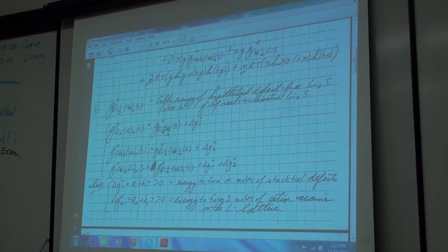Is there any relationship between the site fraction of the vacancy in the cationic sublattice and the site fraction of the lithium in the interstitial sublattice? Well, no, it depends on which side of the stoichiometry you are. They're both dependent on the overall composition. But yes, there definitely is, because you can't just create as much of one as you want. There's an equilibrium constant between them. Okay, so can we use equal site fractions, like only x or only y, because here we used y and x.